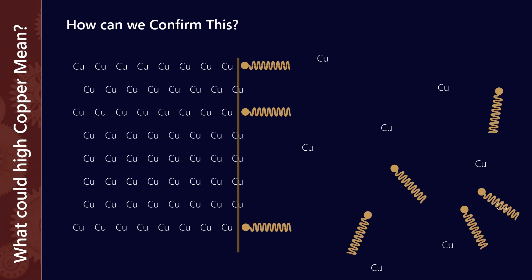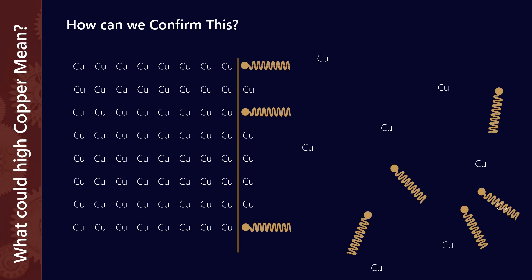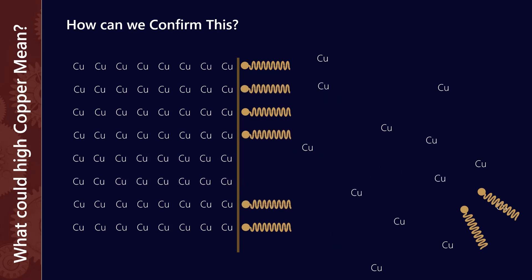As this trend continues and we get more copper migrating into the lubricant we'll also have more metal deactivators occupying sites and that means that the rate of copper dispersion in the lubricant is going to decrease and that's why we see that decelerating pattern.